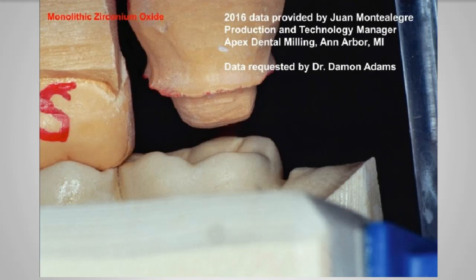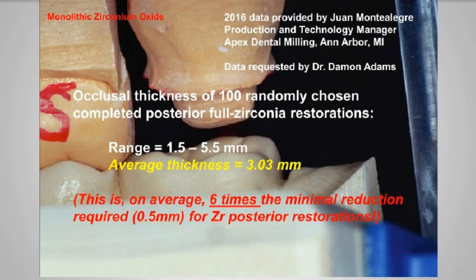So we got some data provided by the Apex Dental Milling Center. I requested it. I had them look at 100 randomly chosen cases, completed posterior full zirconia restorations. I want to see how thick these are. The range was 1.5 to 5.5 millimeters. The average thickness was just over 3 millimeters.